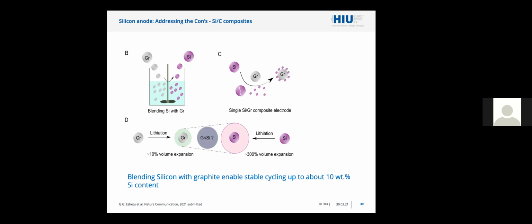However, just to go back and talk about graphite again, a good approach has been found to disperse silicon nanoparticles in combination with graphite, okay? Because in a sense, the SEI forming on the graphite material is also including the silicon particles. Silicon nanoparticles are very small, so they don't break too much. And this is an approach that actually led to pretty stable composite electrodes containing silicon up to maybe 7 to 10%. So far, 7%, I think, is the highest demonstrated in a commercial cell.